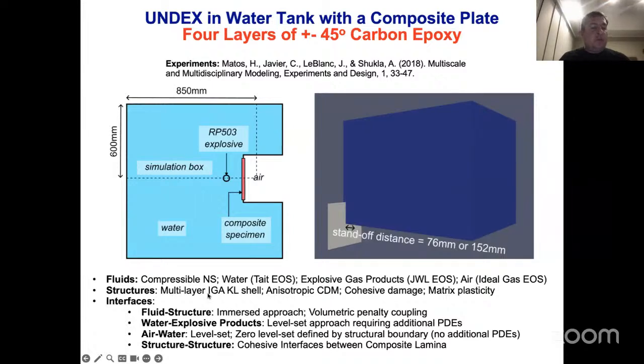We want to be flexible, to be able to handle a variety of structures. In this case, I'm going to show you some results using the multi-layer isogeometric Kirchhoff shell theory, but we do other things. And the challenge is that you have many interfaces in this problem. You need to keep track of the interfaces between fluid and structure. We're using an immersed approach. You have an interface between water and explosive products, which is done through a level set technique. Oftentimes, the structures are air-backed, so you also need a formulation for air and how that interacts with the rest of the system. And in these multi-layer structures, as I showed you, you have to keep track of the interaction between layers, and this is done through cohesive interfaces.